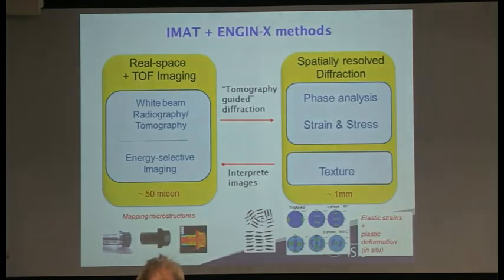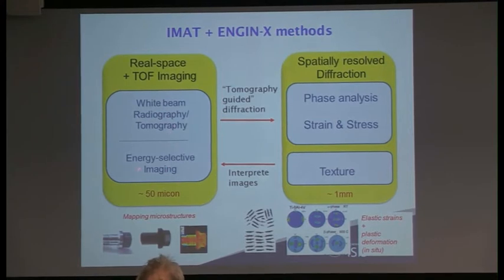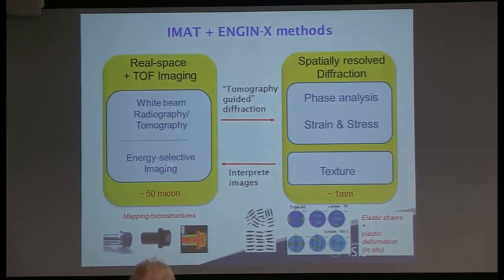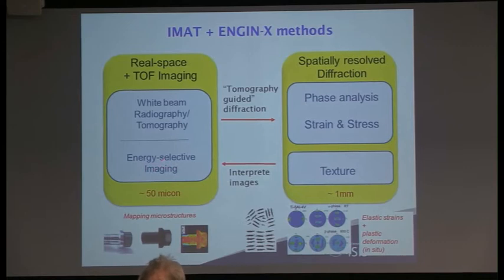So what are our options on IMAT and ENGIN-X? We have the transmission mode, so we want to do white beam imaging and conventional radiography, tomography, but then also measure as a function of energy, so energy selective radiography, tomography. And I will show in a minute that this will allow us to do a kind of microstructure analysis, so we can, for example, map strains in the nickel bolt.